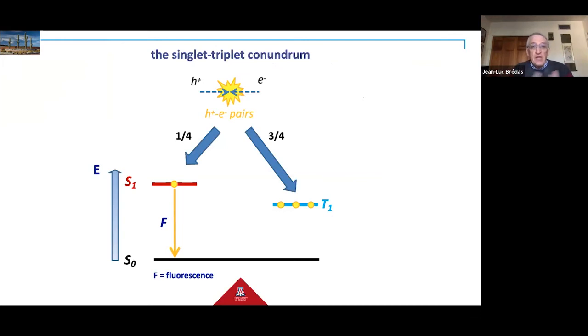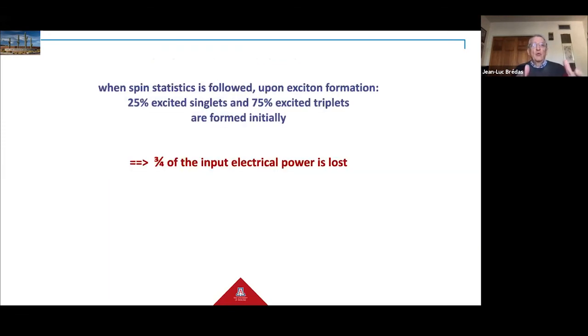But immediately we get to the singlet-triplet conundrum, which is the fact that since there is no correlation between the spins of the injected holes and electrons, when a hole meets an electron, they form a singlet exciton only 1/4 of the time, and 3/4 of the time they form a triplet, which in these fluorescent materials is a dark state, which doesn't emit and decays non-radiatively to the ground state. And this is the reason why one wants to go away from those fluorescent materials, since when spin statistics is followed, 3/4 of the input electrical power is lost right off the bat.